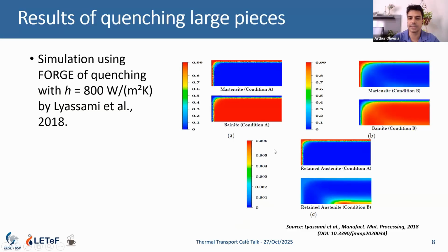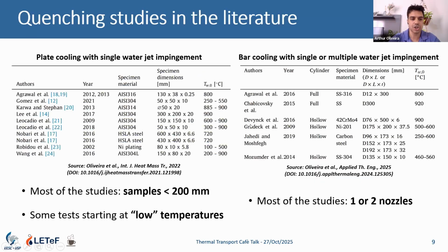For large pieces, there is this simulation, for example, by Lyassami and colleagues, where we can see the martensite formation. It's very stable, very easy to form near the surface, but in the core it's not that easy. So that's what motivates a lot of research on quenching process in general in the literature.